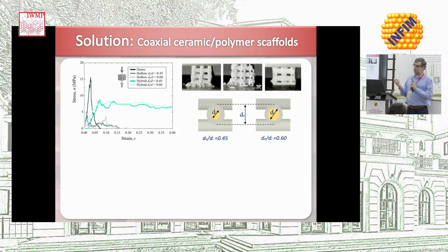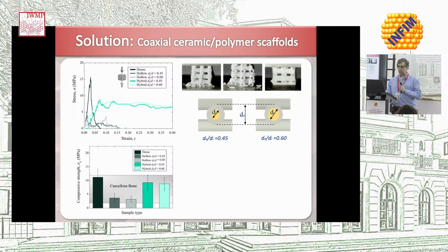What about the mechanical properties of this material? Well, we tested that using two different configurations with two different sizes of the internal channels. Some of them with 40%, occupying 40% of the struts, some others with 60%. And as you can see on these stress-strain plots, there was already an increase in the toughness, but I will try to disclose this a little bit more slowly.